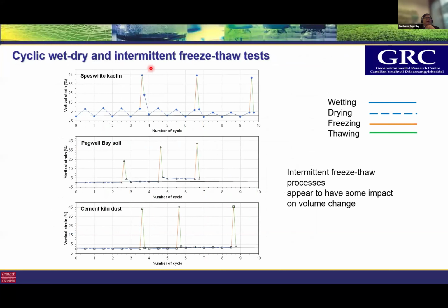We've got a cyclic wet, dry, and intermittent freeze thaw test. That means the materials were taken through wet, dry cycles, and suddenly you're introducing a freeze thaw kind of weathering pattern. The response was a little bit different from what we observed in the cyclic wet, freeze, thaw, and dry test. With wet, dry cycles, you get swelling and shrinkage, and then you got a frost heave, thaw settlement, and then you got shrinkage to this level, and then swelling and shrinkage, and that is how it continued.